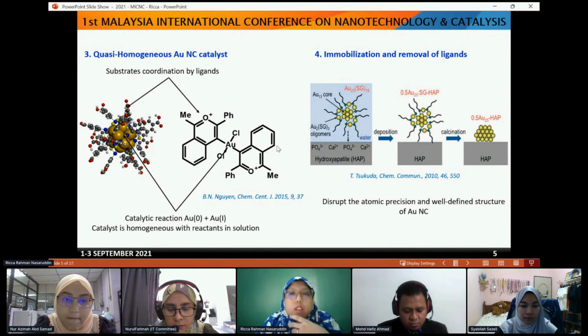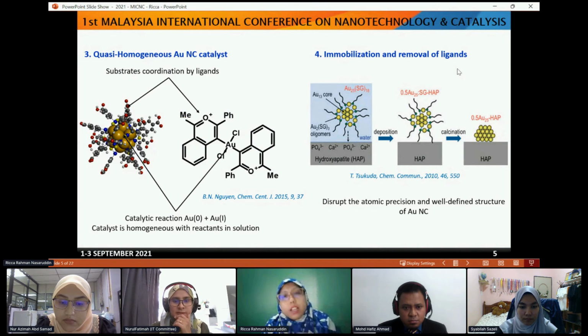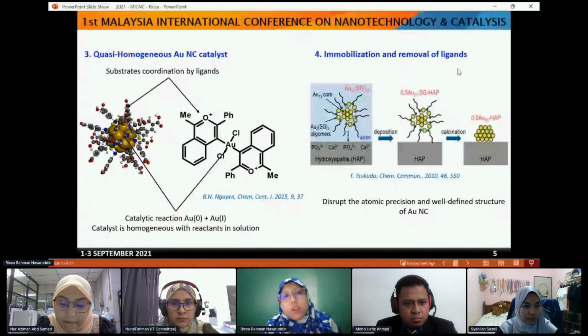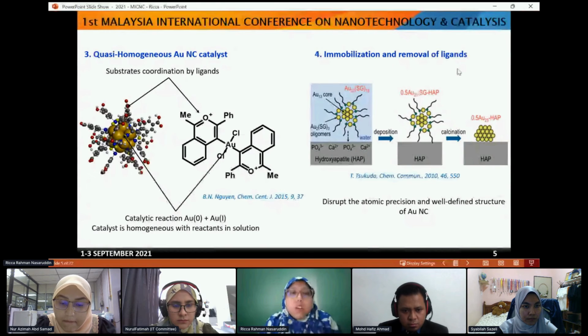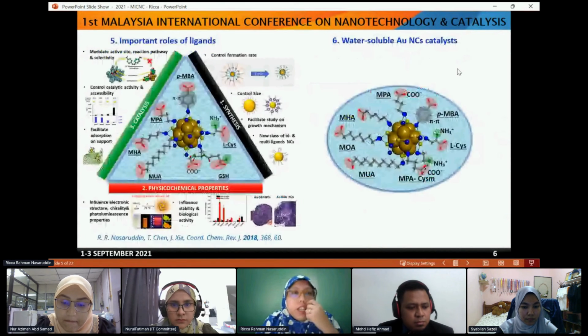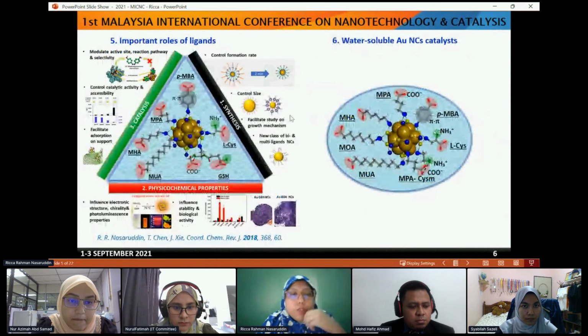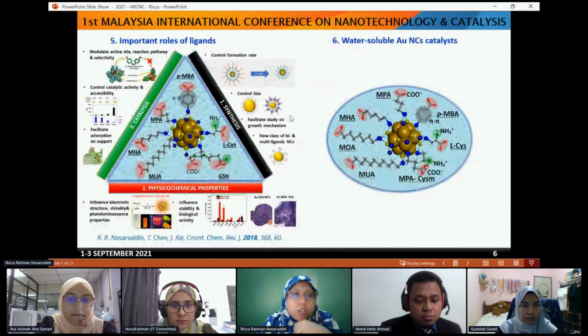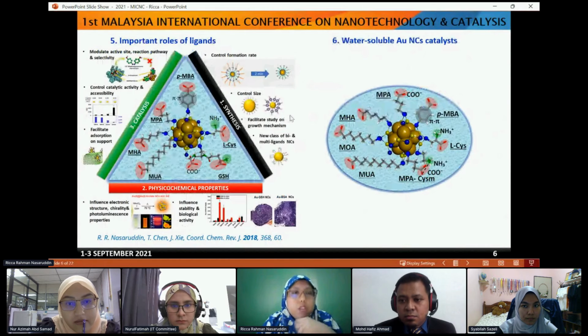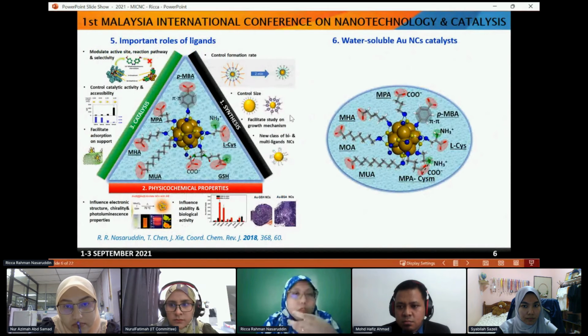Not only that, if you are going to do the immobilizations and you remove your ligands, you can have a smaller catalyst on the support material. And as I mentioned before, the smaller the catalyst, the higher the surface area and the more reactive the catalyst for catalytic reaction. And then another good feature of this ligand-protected gold nanocluster is that you can also study the important roles of the ligands.